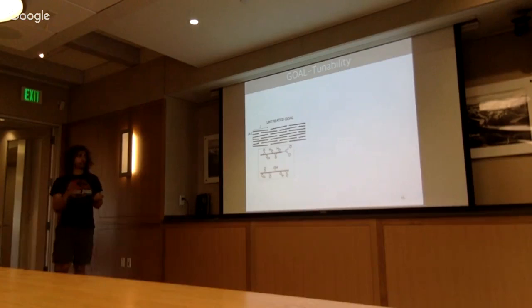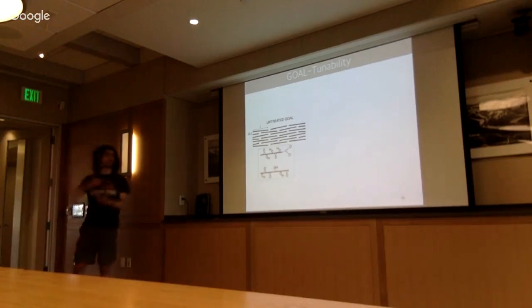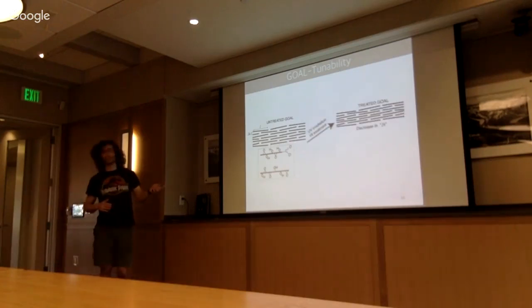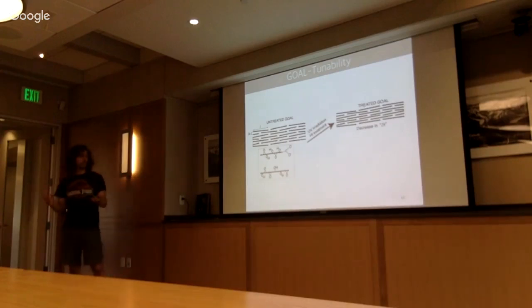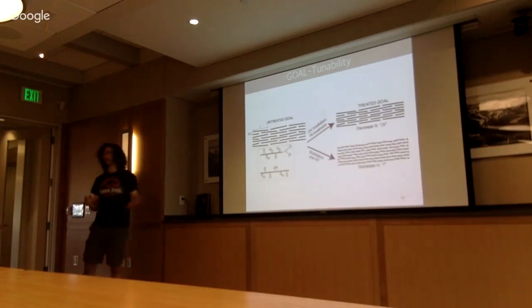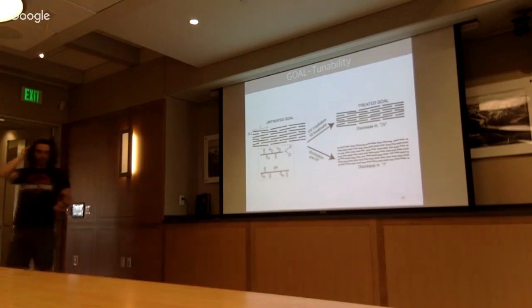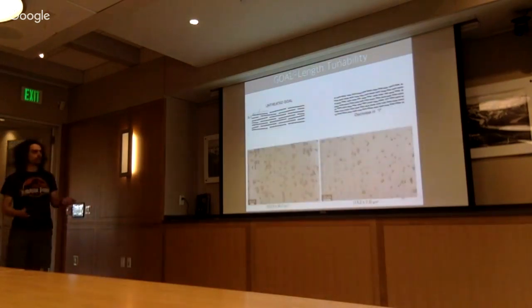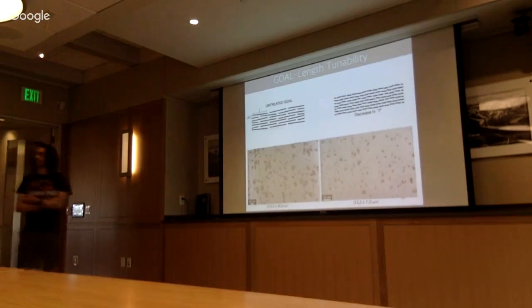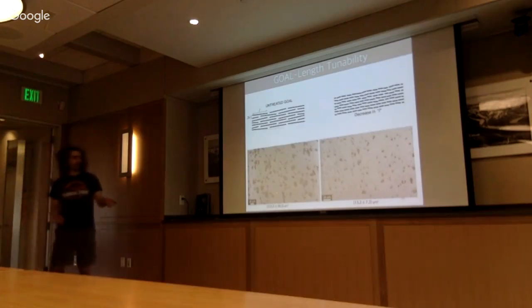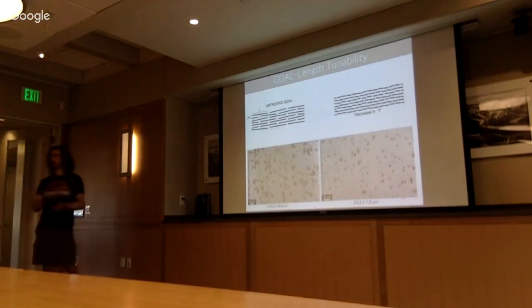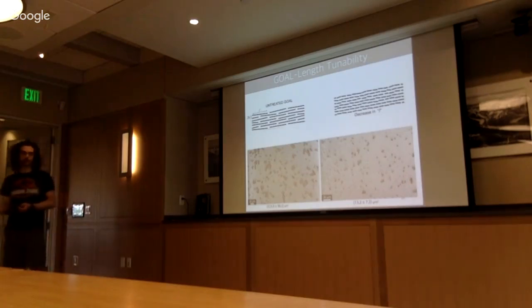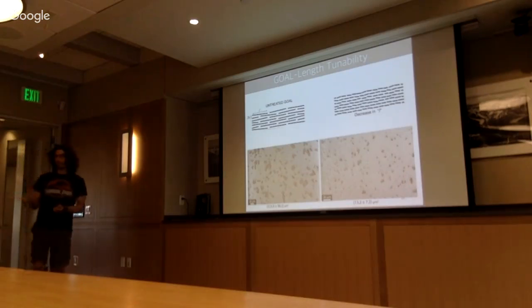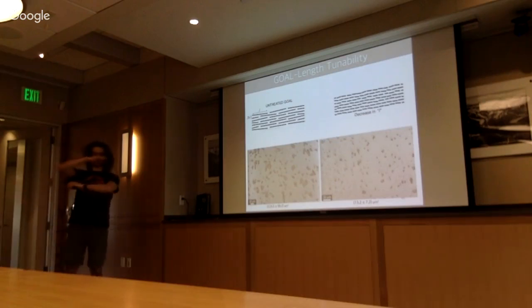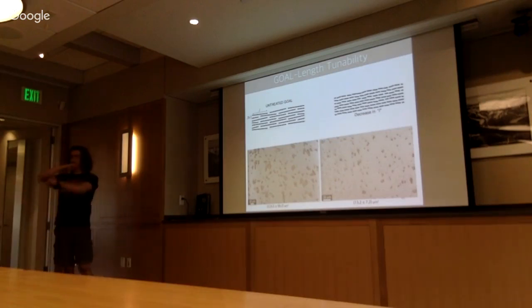How are we going to do that? So first of all, we can just smush the structure. So you see the separation distance is decreased. Or what we can do, we can change the flake size. And how can we do that? We can change the flake size with ultrasound irradiation. So you see big flake size compared to smaller flake size. Here we're reducing the size about an order of magnitude. Changing the chemistry, or basically reducing the separation distance, is a bit more complicated.